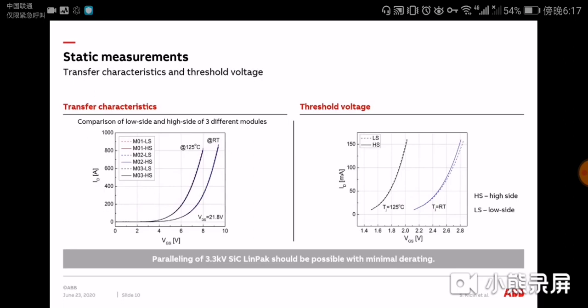Modules transfer characteristics and threshold voltage are shown on slide 10. Measurements were done at room temperature and at a temperature of 125 degrees C. The transfer characteristics were measured on 3 different modules. It means that the picture on the left shows currents measured on 6 different switches.